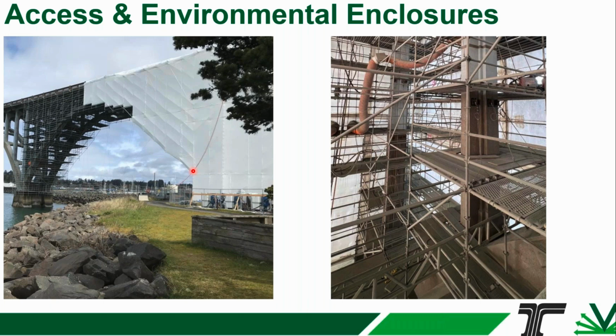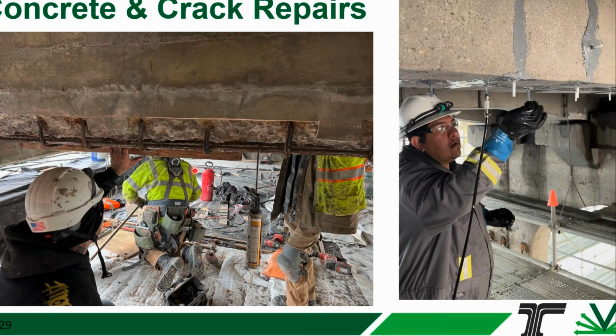There was very little concrete damage that had occurred over the 28 years that the system had been running, but there were some concrete repairs that were required, and those concrete repairs were done using traditional concrete repair materials and traditional concrete repair techniques, the same as would be recommended by the International Concrete Repair Institute, or ICRI, and covered in some of the various AASHTO specs as well. So concrete removal and replacement where the concrete is delaminated or no longer functional. And on the right-hand side here, some crack injection, which was done by epoxy crack injection.